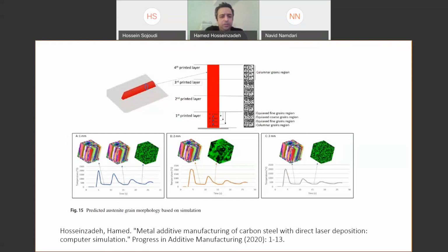These are stochastic simulations with cellular automata. You can see after the first peak and second peak, we have a columnar structure, and at the end, we have newly nucleated austenite phase or grain. This is a steel, because I said austenite. New grains grow in the columnar structure, and at the end we have an equiaxed grain structure.